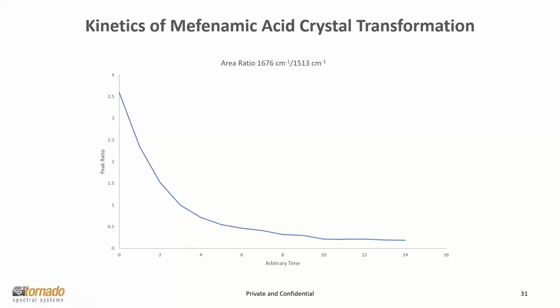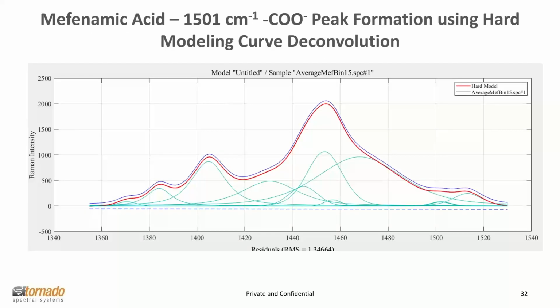So if we look at that again, we can look at the kinetics a little bit differently. If we ratio to that band, the kinetics become a little more defined. But we can also do other types of analyses that give you more information. So again, if a simple trend analysis is what you're after, that's possible. But if you want to understand more and delve into the data, you can oftentimes dig out quite a bit more information about your process as you look at the spectrum more carefully.